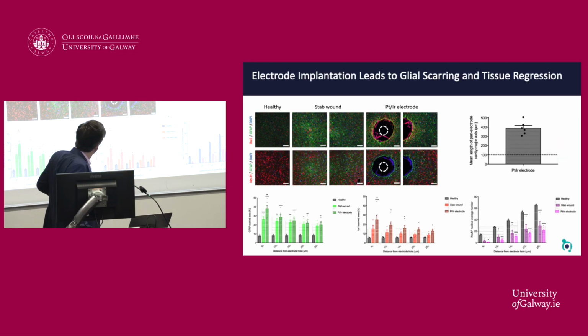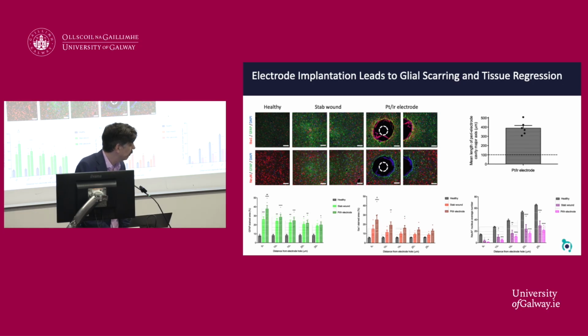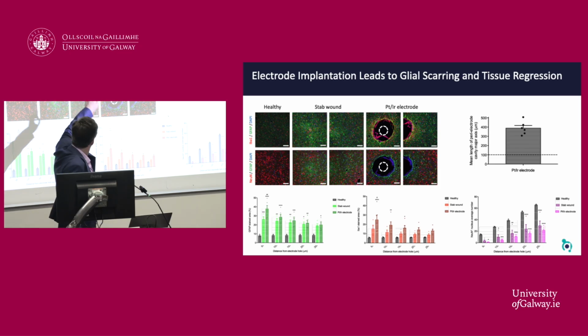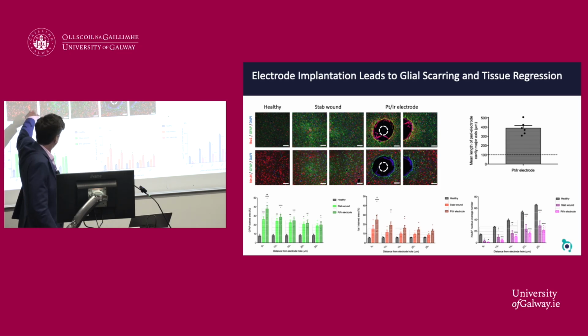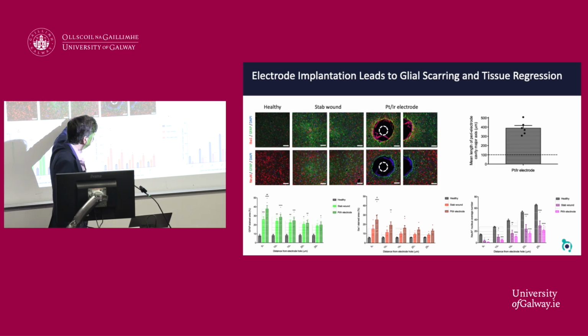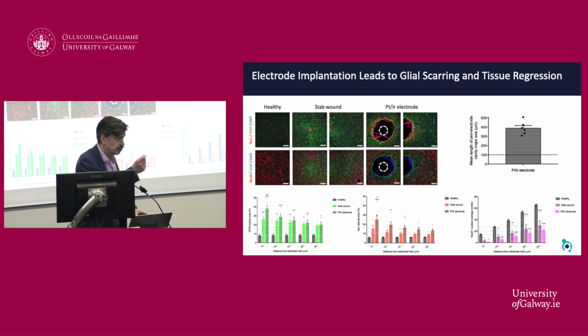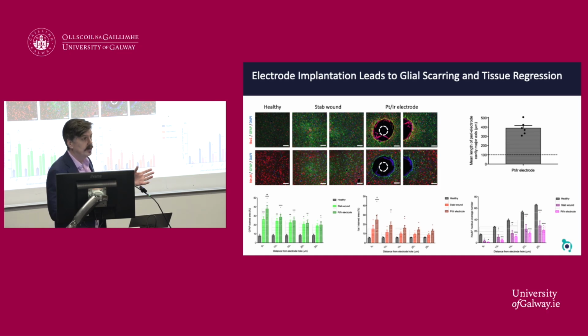We then went on to show that this was in fact true in vivo. So we performed in vivo analysis with rats, where we have 2 control groups: healthy rat brain tissue, and a stab wound, which is just an electrode that's stabbed into the brain and removed, and the brain is allowed to recover. Then there are electrodes that are kept in situ for up to 8 weeks. And we found that, yes, of course, we expected to see astrocytes become angry and activated, microglia become activated, and the neurons start to die.